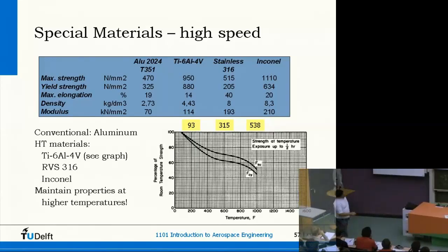If you look at the properties, we also have to look, of course, at the temperature relationship. And here you see, for instance, the temperature relationship of a titanium alloy. This is about room temperature. And here you see this is about 540, 600 degrees. So the strength decreases by a factor of 2. You have to keep that in mind if you are designing an aircraft like that.